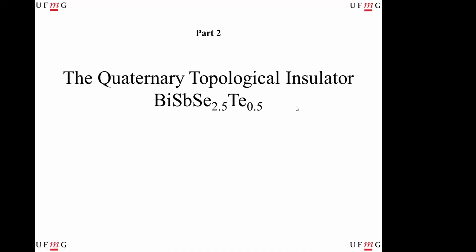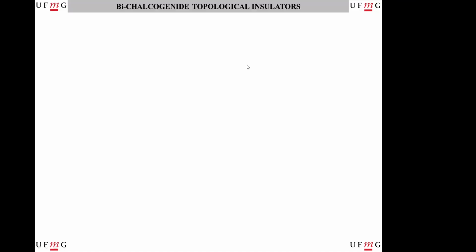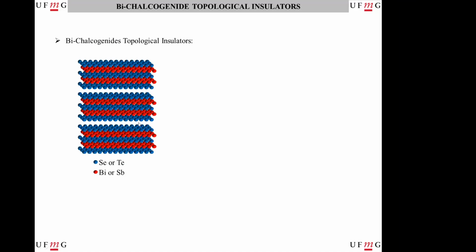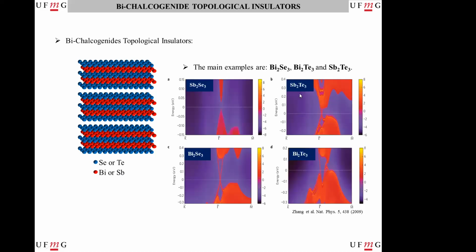So the second work is the quaternary topological insulator bismuth antimony selenium 2.5 tellurium 0.5. Bismuth selenide is part of a class of materials called the bismuth chalcogenide topological insulators. They all have the same structure of quintuple layers, but different from bismuth selenide, the blue atom here could be selenium or tellurium, and the red atom can be bismuth or antimony. The main examples here are bismuth selenide, bismuth telluride, antimony telluride, and antimony selenide. We saw that from these, three are topological insulators, so we can see the states crossing the band gap here, but antimony selenide is not a topological insulator, just a regular semiconductor.